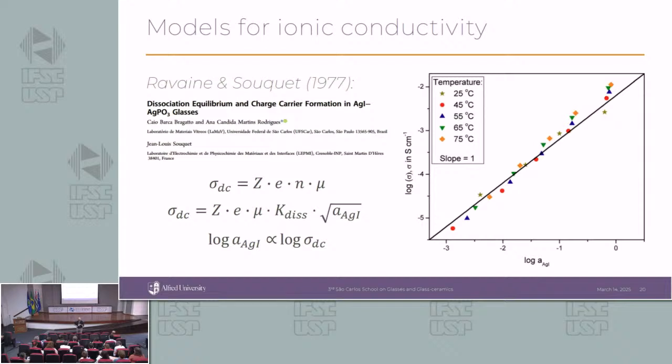It's going to be the effective concentration. So I'm talking about the concentration of the dissociated ion here. And you can see that, again, in the work that we published here in Lamav, there is a linear dependency between the activity and the ionic conductivity. Very interesting results. We start showing this relationship, and maybe this idea of not every alkali can move is giving us some good results.